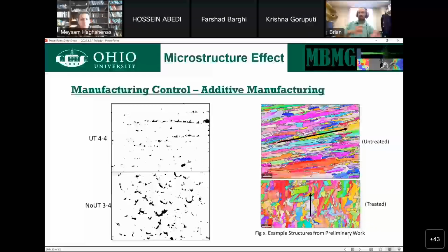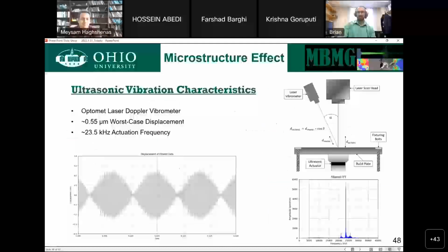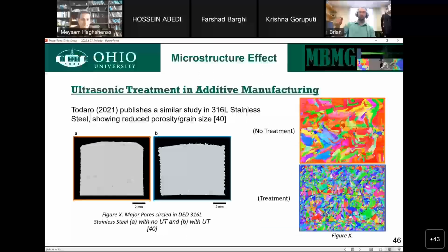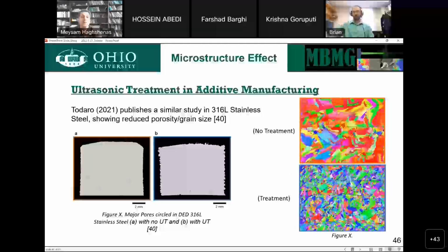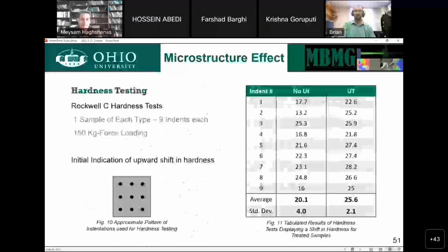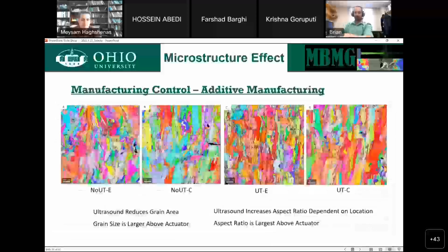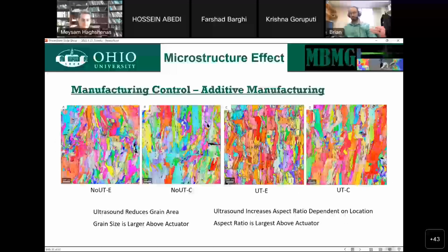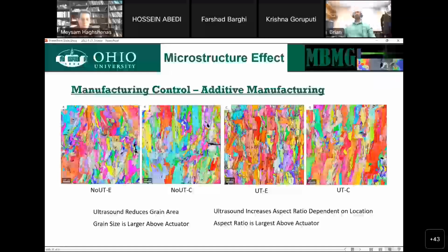And so, if you use the same equations that they use to estimate the intensity needed to cause this, you would need significantly more energy. For the case where we had grain shape change, we were just barely above the theoretical cavitation threshold for nickel 718. The studies where you can really see the difference in size were orders of magnitude above that point. And for the last result that you see here, we were below the theoretical cavitation threshold.